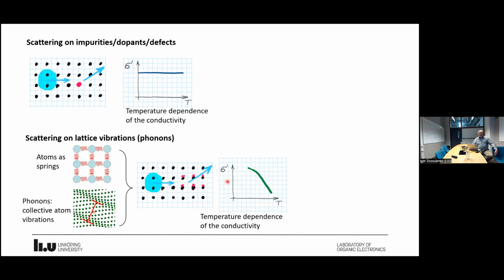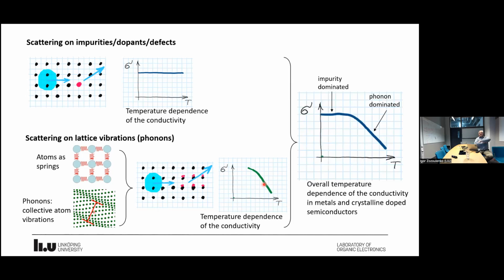And when you look at the temperature dependence of the conductivity, you will find that the conductivity decreases with the temperature. This is a very natural result, because the larger the vibrations of the lattice, of course, the stronger will be the scattering. So to summarize, if you look at the conductivity of metals or highly doped semiconductors that behave like metals, this would be the typical temperature dependence. At low temperature, conductivity is impurity dominated and does not depend on the temperature. And then at higher temperature, conductivity decreases. Okay, so this was the band transport.